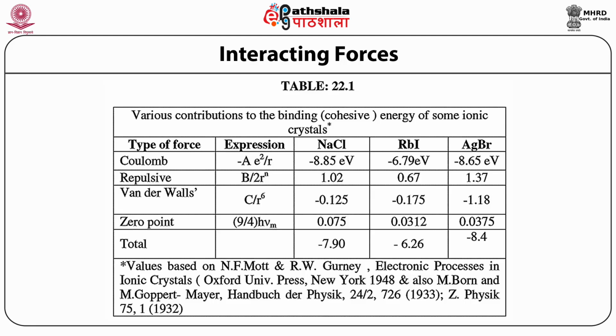Now the type of van der Waals forces, the expression capital C upon R raised to power 6, for NaCl minus 0.125, for RbI minus 0.175, for AgBr it is minus 1.18. Zero point expression is 9 by 4 h into nu subscript m. For NaCl it is 0.075, for RbI 0.0312, for AgBr 0.0375. The total for NaCl is minus 7.90, for RbI it is minus 6.26, for AgBr it is minus 8.4.